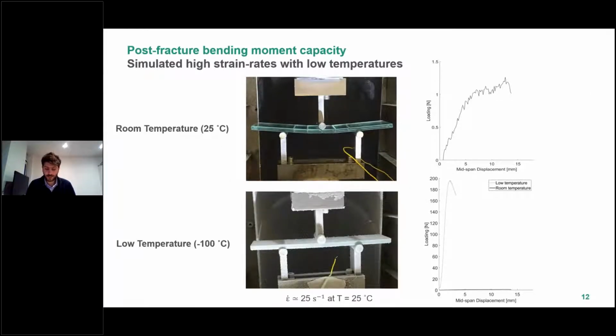Quasi-static bending tests of pre-fracture specimens were therefore performed at -100 degrees Celsius and were compared to room temperature tests to assess the influence of high strain rates. An idealized pre-fractured pattern was considered with the cracks aligned in both glass layers and spaced every 20 millimeters. Using the mapping equation derived, a maximum PVB strain rate of 25 per second was calculated at a temperature of 25 degrees Celsius, which is a typical value expected under blast loads.